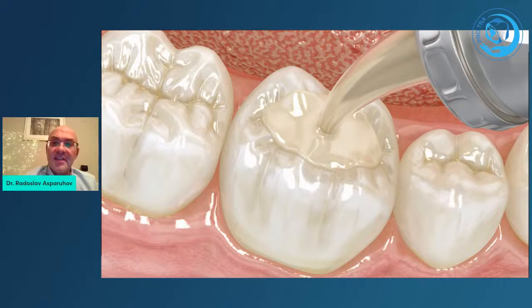Glass ionomers are materials that can be placed in bulk, and that is their biggest advantage. Of course, there are also bulk fill composites, but they do remain composites. They do shrink. They do cause stress during this shrinkage. While the glass ionomers have a very, very small shrinkage, and the stress is negligible. So I always put the glass ionomer in bulk and wait for a certain setting of the material. Rather than giving you an exact number, I would tell you, look at the surface. When the surface becomes matte or dull, when it's not shiny anymore, that is exactly the right time to do the occlusal modeling of the restoration without the material being sticky.